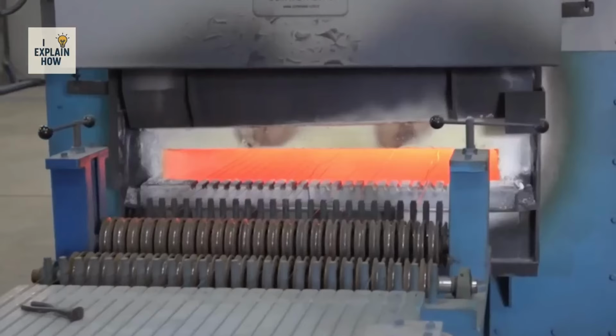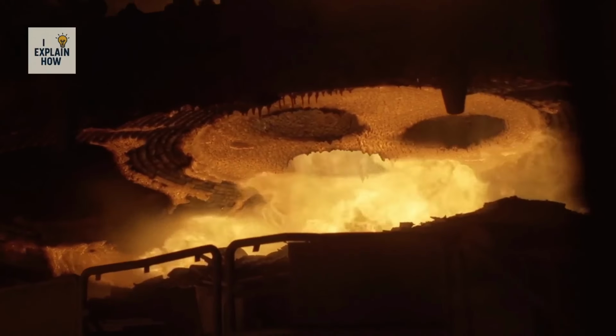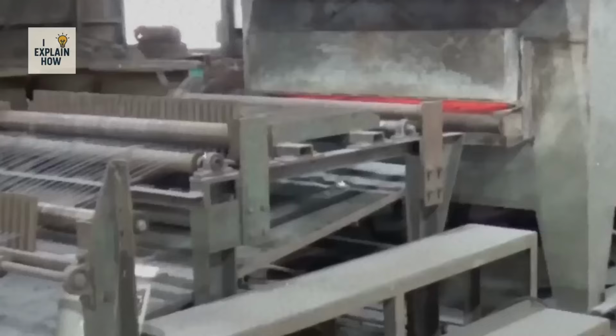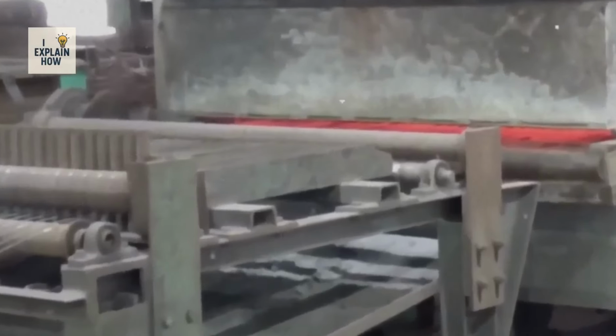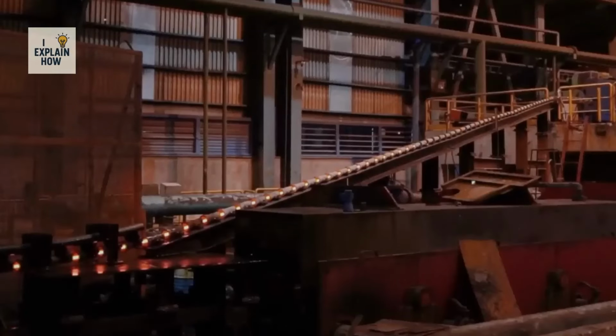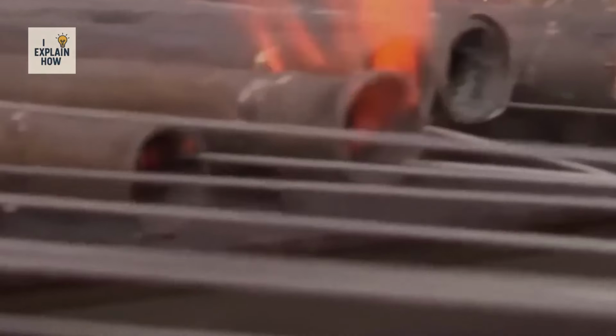To fully meet the mechanical requirements, the wire must undergo a crucial step: heat treatment. It is heated in a furnace at very high temperatures, between 400 and 800 degrees Celsius, in a strictly controlled atmosphere. The heat modifies the internal crystalline structure of the metal, reorganizing the grain network to achieve an ideal balance between hardness and elasticity. Once the desired temperature is reached, the wire is immediately cooled by air jets or immersed in an oil bath, thus fixing its new structure.